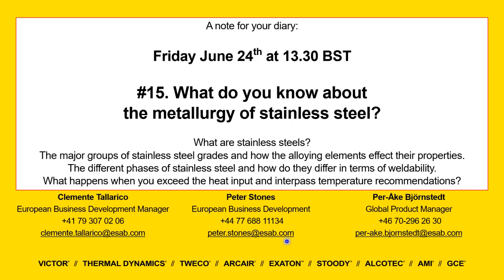I would agree with that. I mean, if you do a perfect pickling of the surface and you restore the chromium oxide, so you have a passive layer on the weld and the surrounding of the welds, and that it's the same as the base material, then you would not need to have this passivation treatment.